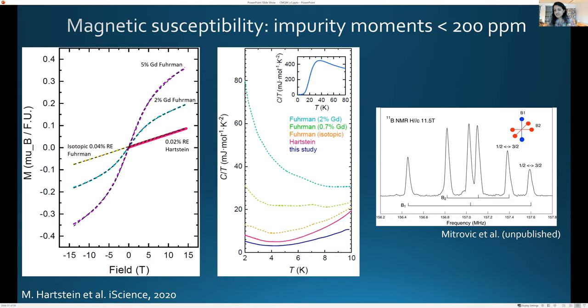So it means one of two things. Either the material is completely homogeneous and there's no impurity distribution, or very little impurity distribution, or it's completely impurities which are homogeneous. But if it was completely impurities which are homogeneous, one would get metallic behavior, which one doesn't. One sees very good insulating behavior. So the conclusion is that there's no observable inhomogeneity in the material, which argues against any of these patches of metallic inclusions, which could conceivably give you some small oscillations.